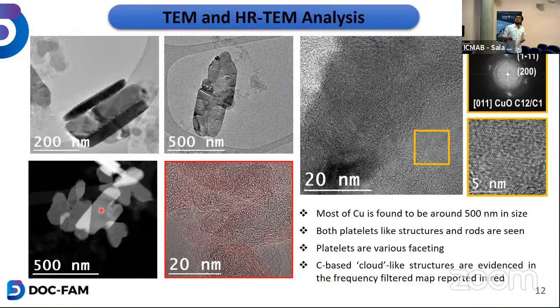So these are platelet-like structures, and the platelets we have seen are of various faceting, like 200 facets, 111 facets, and 311 facets as well. And in this pattern, we can see the idea of having carbon in this catalyst material: carbon has to surround all the copper nanoparticles and increase the conductivity by better exchanging the electrons between them. Thereby having more electrons to mediate the next products, because ethylene requires almost 12 electrons. So from CO2 to CO intermediate, and then to ethylene, it requires almost 12 electrons.